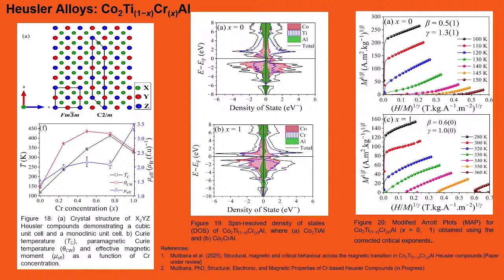One, it rests in effect on this theoretical calculation of the density of states. Where does the unbound electron sit in an electronic level? Pure cobalt, titanium, aluminium effectively have a little gap. There's a little gap there in the one spin state, and there's another gap here. The material, which is a metal, seems to react almost like a semiconductor. It goes in that direction.